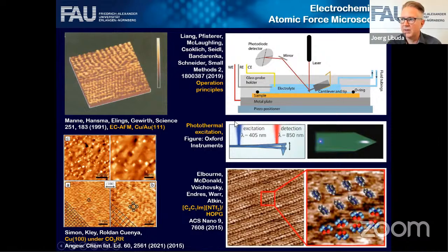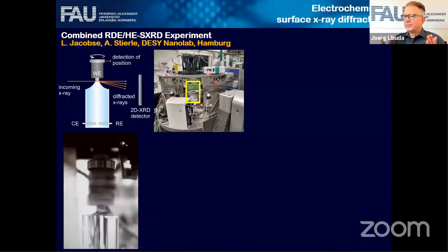That's not what you use in electrochemistry, but there's also been a lot of progress in electrochemistry. For instance, what's commercially available are setups where you do optical excitation of the cantilever. And if you do this excitation optically instead of with a piezo, this experiment is much more stable in the electrochemical environment. And here are a few examples from Beatriz Roldan's group, for instance, copper 100 under CO2 reduction conditions. And here, this is the interface of an ionic liquid, also with molecular resolution, from Rob Atkin's group. This shows that you can achieve a lot with this experiment.